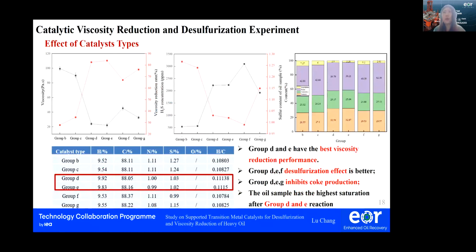Next, we will investigate the effect of different types of catalysts with different loadings on the viscosity reduction. And the oil sample is prepared on the basis of the presence of hydrogen donor, which is group B. All the viscosity reduction experiments were conducted at the temperature of 280 degrees centigrade.